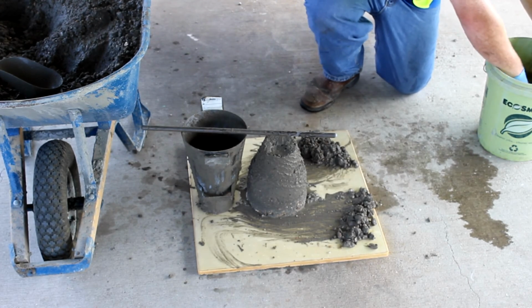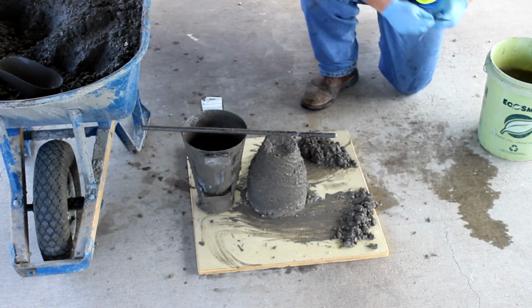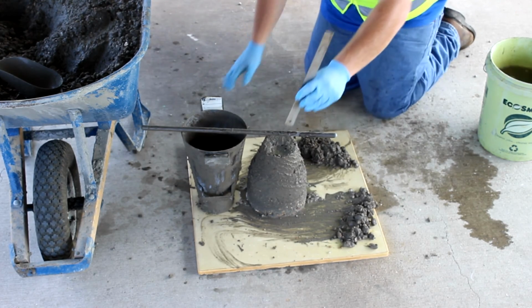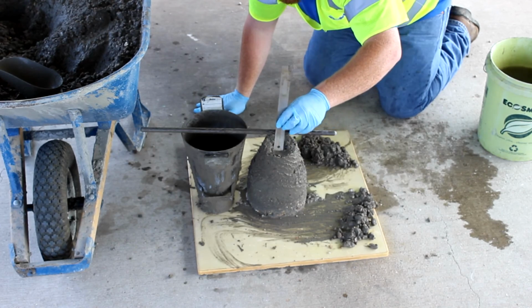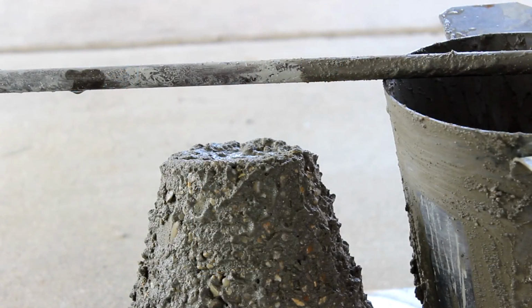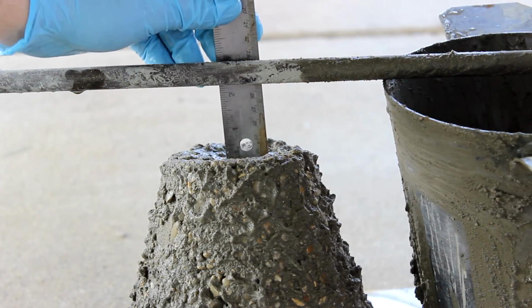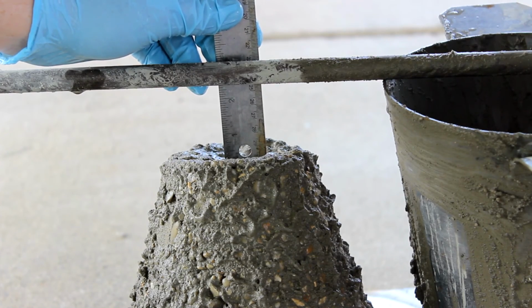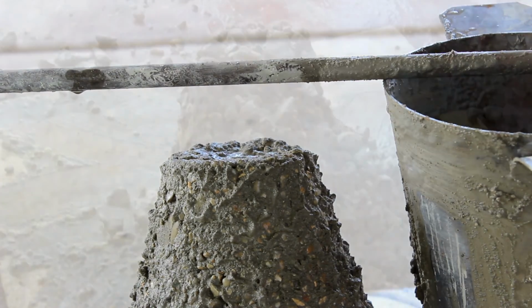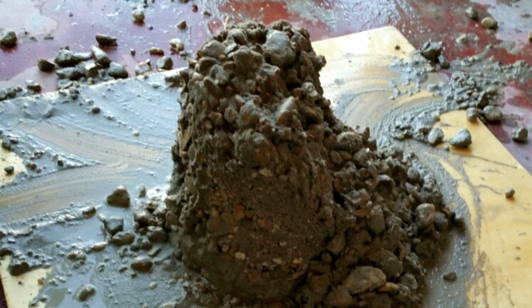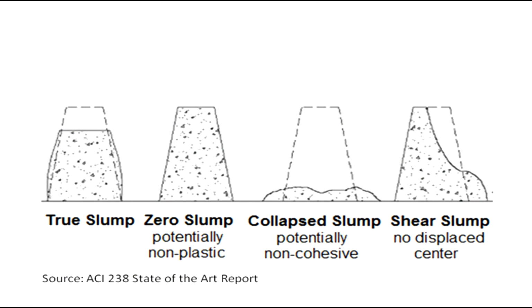Immediately measure the slump. This is the vertical distance between the top of the mold and the displaced original center of the top surface of the specimen. Report the slump to the nearest 1/4 inch. If during the raising of the mold a decided falling away or shearing off of the concrete from one side or portion of the mass occurs, disregard the test and make a new test on another portion of the sample.